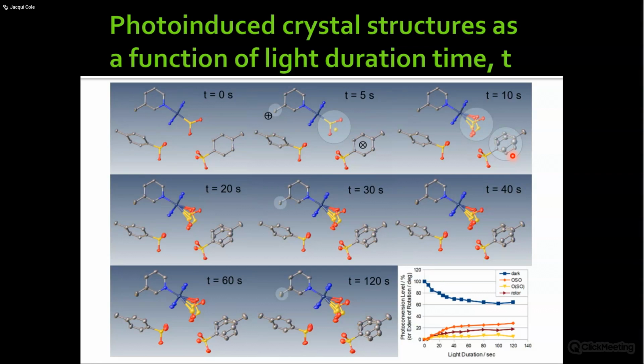And actually this is now the first time, after 10 seconds of light, that you can start to refine more or less the rotation of the arene ring to alleviate the strain. And that makes sense, right? Because the more of this oxygen-bound sulfur that forms, the more the strain builds up. So you're starting to really see it now.